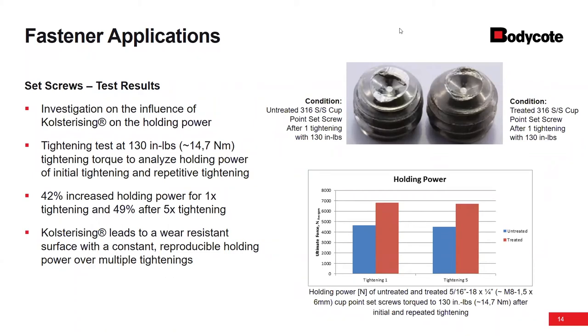Q: Can Kolsterising be used in place of B8M bolts? With our process, we are not improving the overall mechanical strength of the 316 — it's going to have the same bulk material properties as when you started. So if you're looking for a stronger 316 using Kolsterising, it wouldn't get you there. However, we have had customers use 300 series fasteners plus Kolsterising to replace Nitronic 50 and 60 materials, getting a more readily available fastener that will outperform nitronic materials.